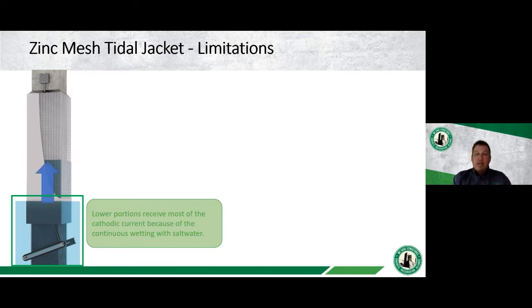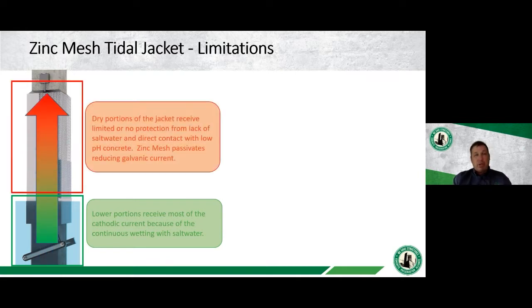Essentially what ends up happening is the lower portions of the jacket receive all of that galvanic protection. And if you remember me mentioning, as we move farther up the pile, we start to move into the areas of the pile where we don't have any salt water present. Without the salt water present, we cannot activate the zinc within the jacket. So the higher we move up, the more passive the zinc becomes.